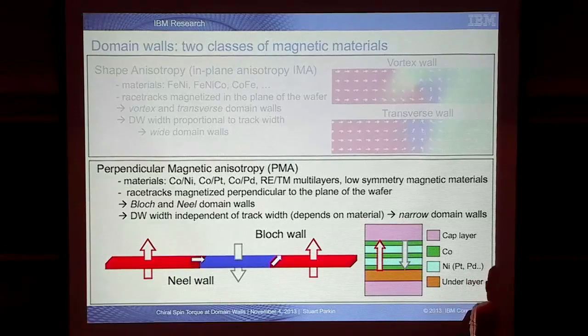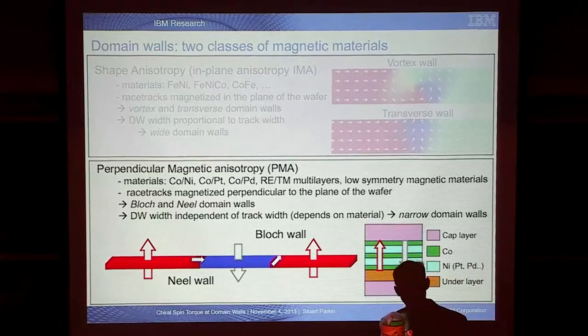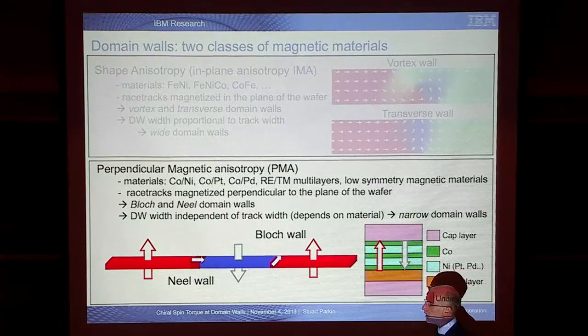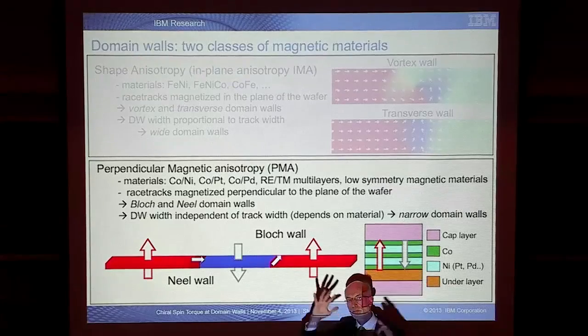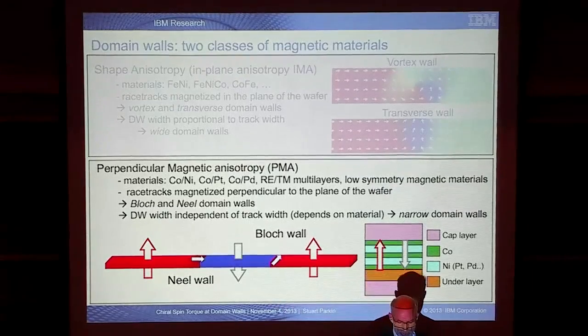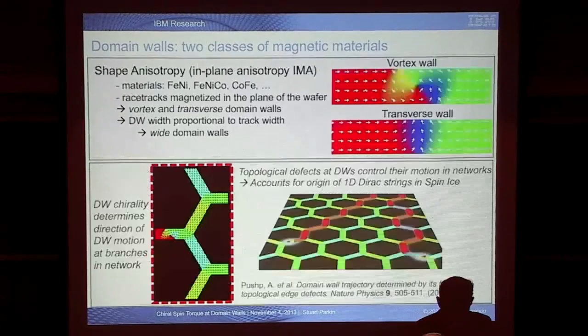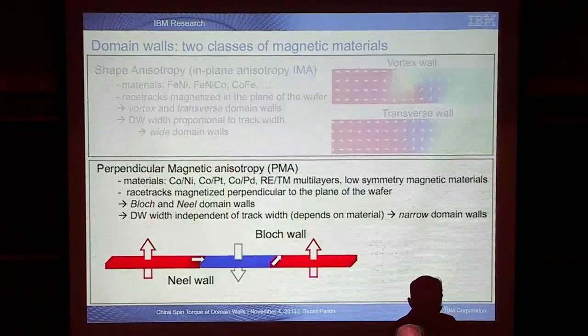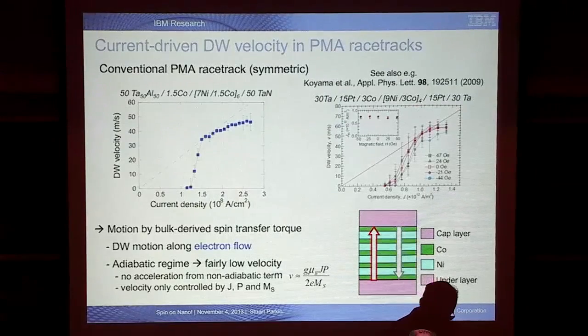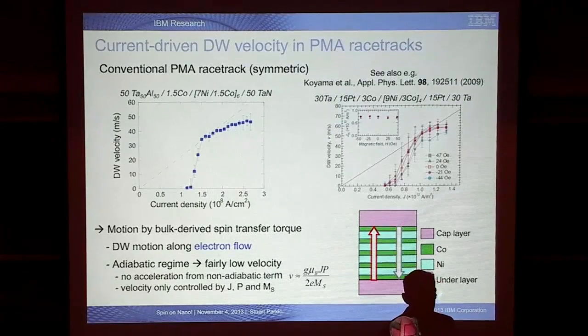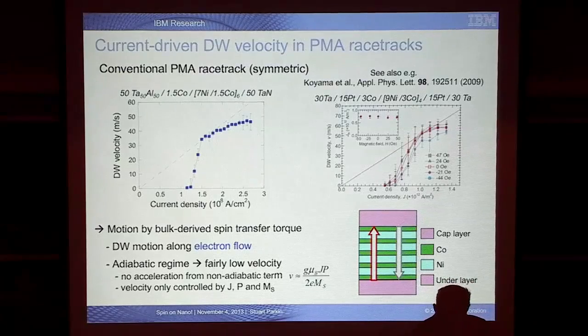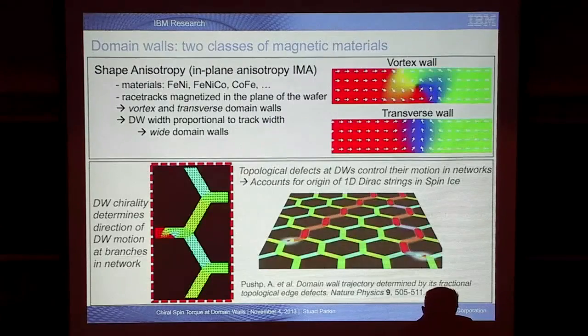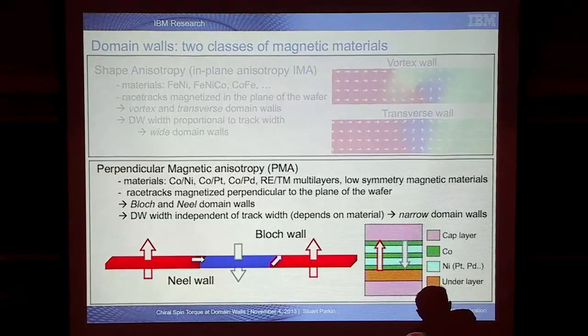And what does that mean? This means that the domain walls can be much narrower. They can be atomically narrow in this configuration as compared to these soft materials. And it turns out that in the last couple of years, we and others have discovered that these, I'm going to skip this, but let's compare briefly. We have these soft magnetic materials, large domain walls. We have these perpendicular magnetized materials in which the domain walls are much, much narrower.